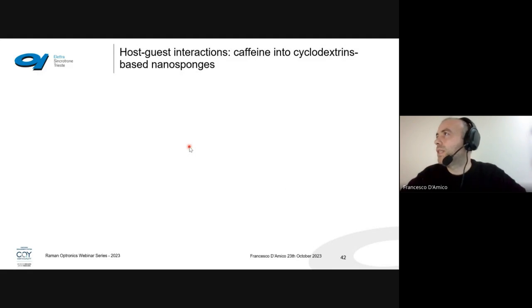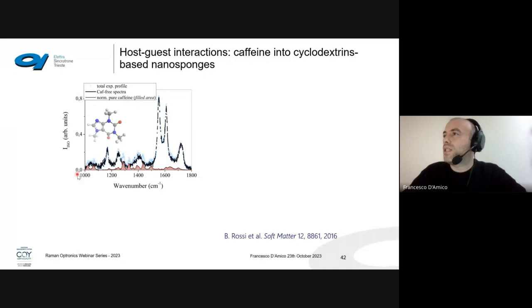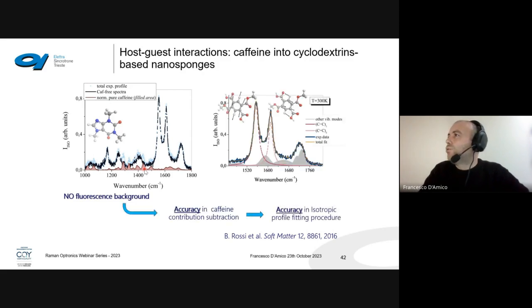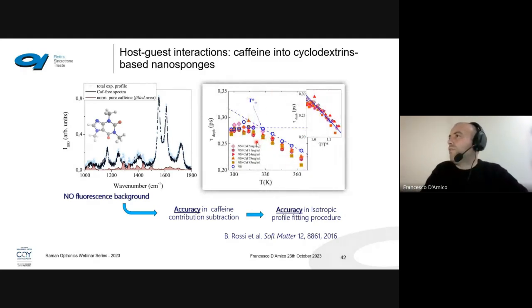Then another small experiment of guest interaction. By exploiting the fact that we don't have fluorescence background, we were able to study the interaction between caffeine and cyclodextrin-based nanosponges. And we are able to see that these spectra are flat. We don't remove anything here. This is not flat, the background, because we have removed a certain kind of fluorescence background or something else, but this is the real data, because in ultraviolet we can avoid the presence of fluorescence background. Therefore, we were able to subtract the caffeine contribution in a very careful way, and then to analyze the peaks, which are Lorentzian peaks, basically, to find from the width of the peak information about the dephasing time, and therefore to study the swelling of caffeine in cyclodextrin nanosponges.